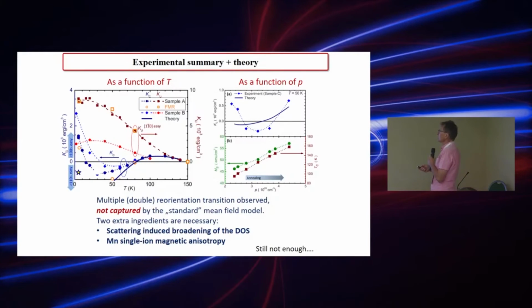So the summary of our findings, because we did the measurements for 3 samples, is the following. Let me start from the less interesting one, the uniaxial anisotropy constant as a function of temperature. It goes like this, and these full points are established from magnetization curves. The points established from FMR are marked with open symbols, and as you see, they coincide very nicely with those established from magnetization. Now when we turn to the blue points, which are the cubic anisotropy, we see that the curve is quite complicated, and it's very funny, but we've got not one but two switchings. So we start from a positive value, then we move to negative values, and then we are in positive values again.